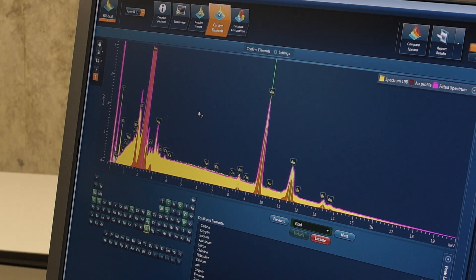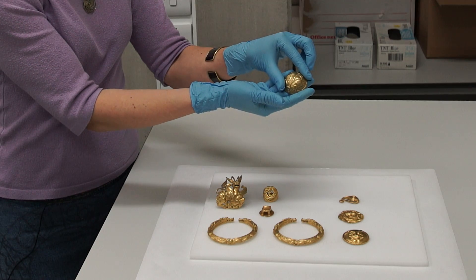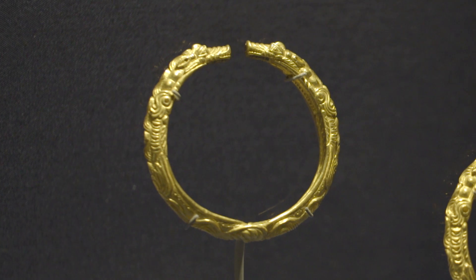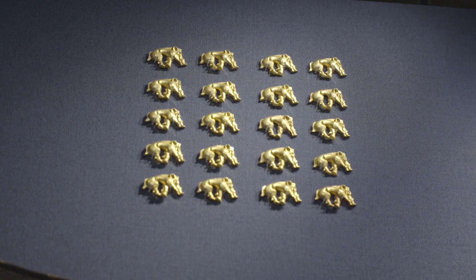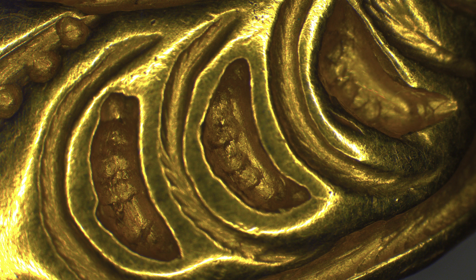What I found interesting is the variety of alloys which have been identified. For example, this particular roundel, which looks a lot greener than the other gold objects due to its high silver content — it has got about 20% — shows that it's an unrefined gold used for this particular object. We were really excited to put the results of archaeological science into the interpretation of this exhibition. One of the most interesting things about this new research was the real proof of the level of skill and the variety of techniques used by the different craftsmen to make these different objects.